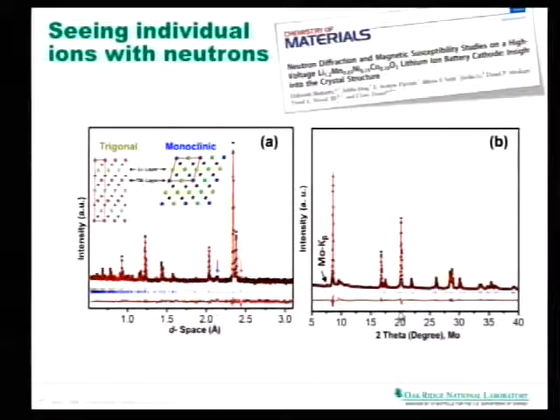This essentially shows two diffraction patterns. On the right-hand side, you have an X-ray diffraction pattern of that phase. On the left-hand side, you have a neutron diffraction pattern. And on the right-hand side, you say, I have a perfect match. I know exactly what that material is. I can determine my phase. I can determine everything I want. In the neutron side, I look here and I see, if I take this pattern, the crystal structure I've calculated with this, and apply it onto my neutron pattern and simulate that, I have some problems.